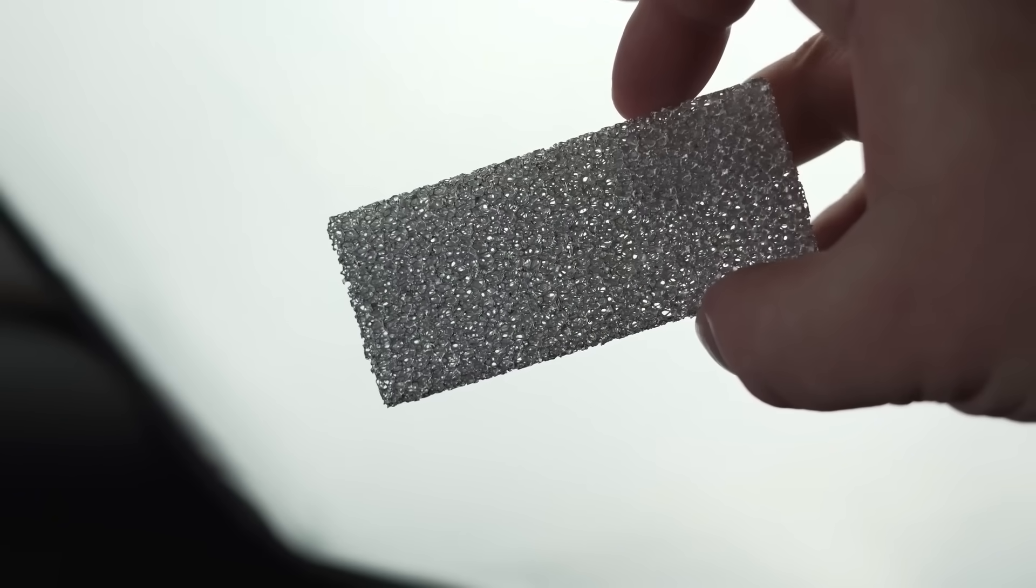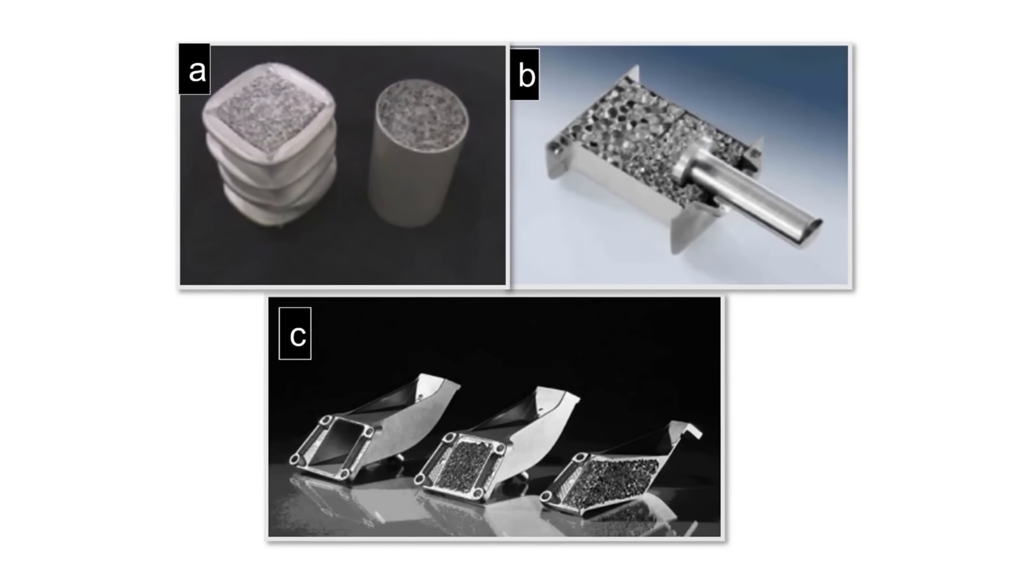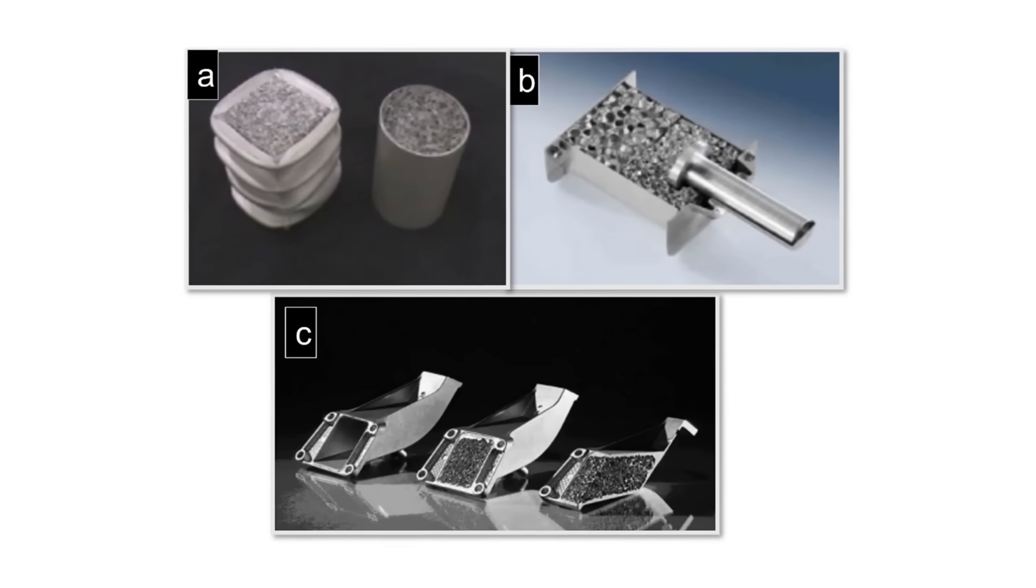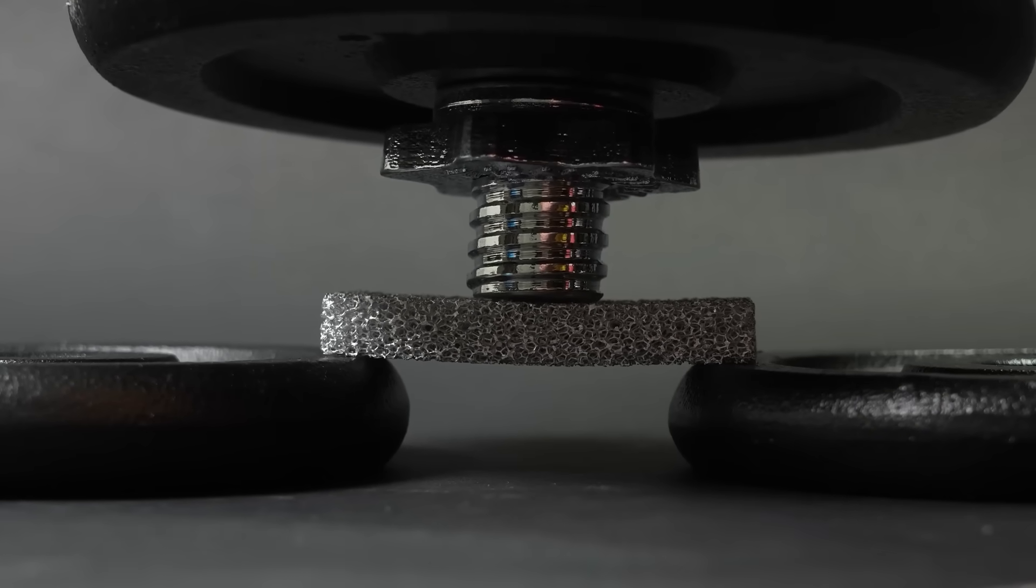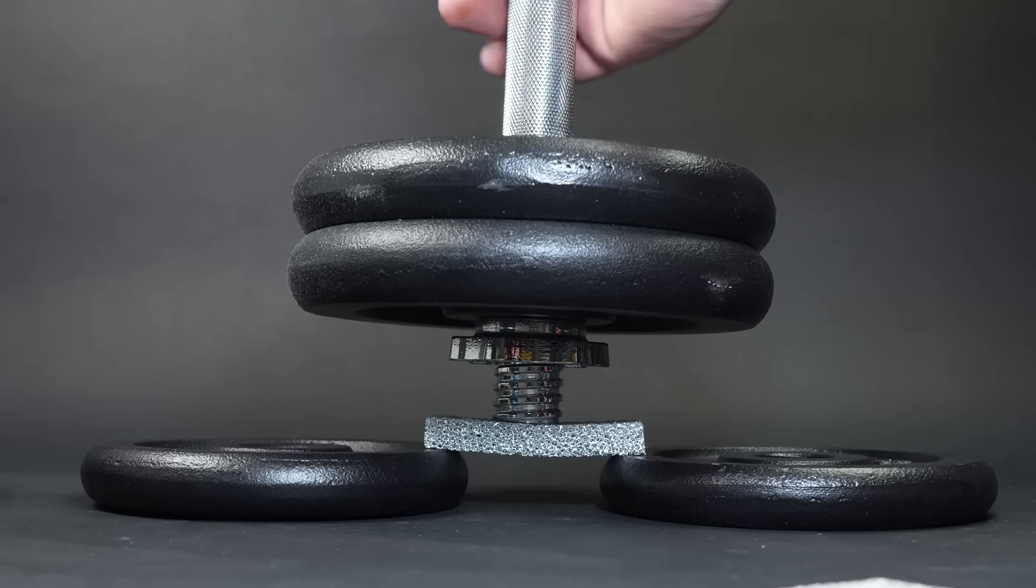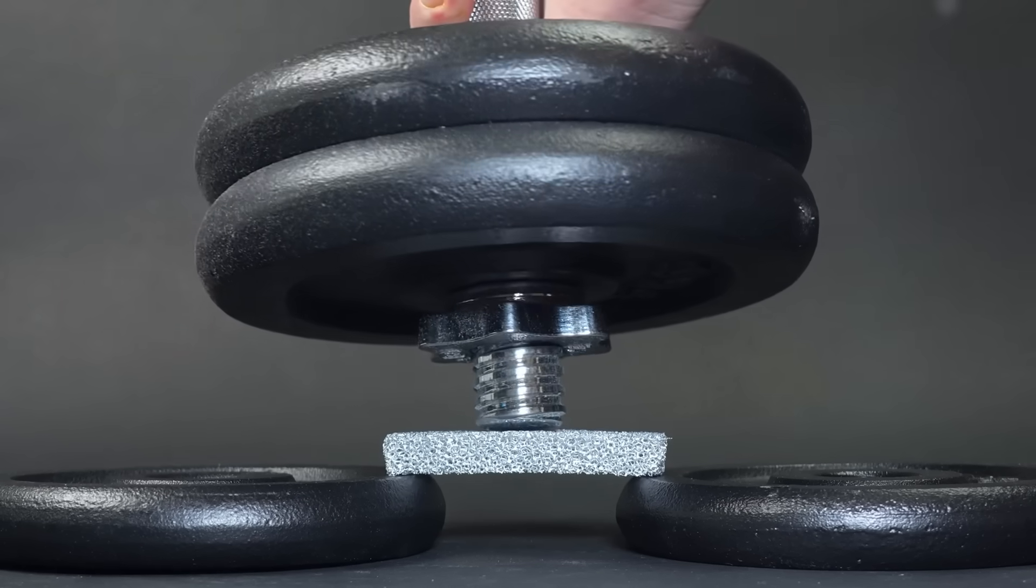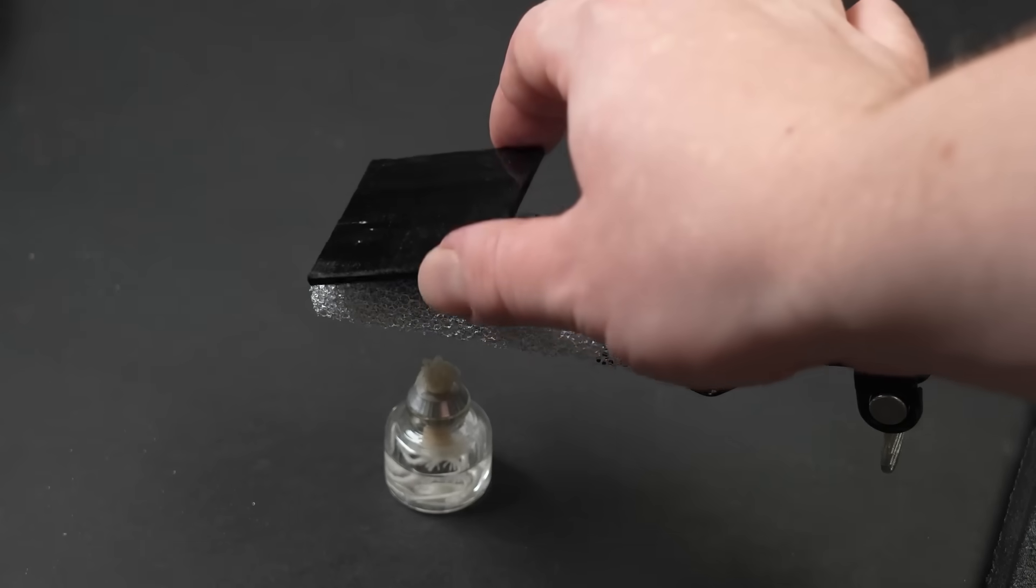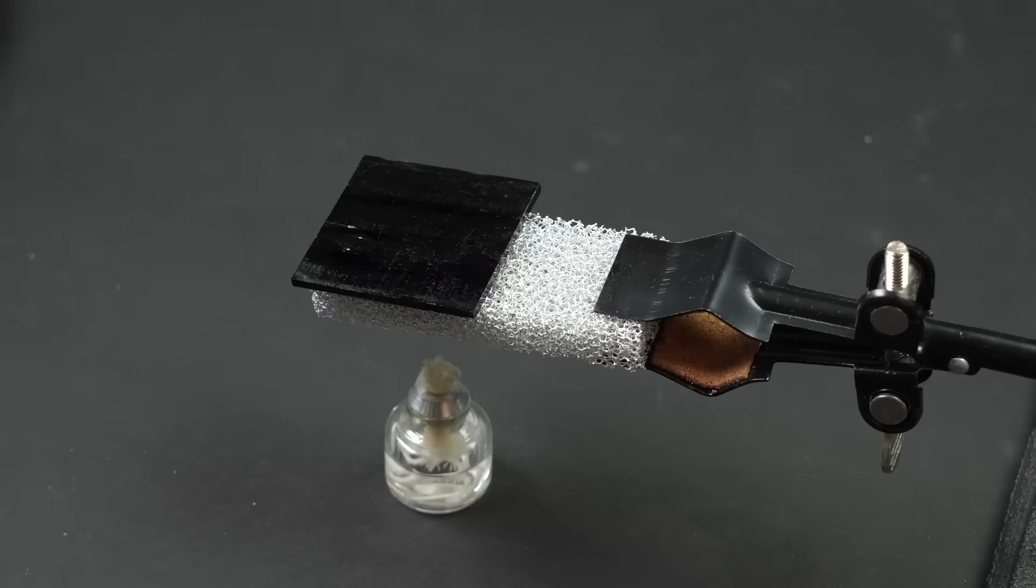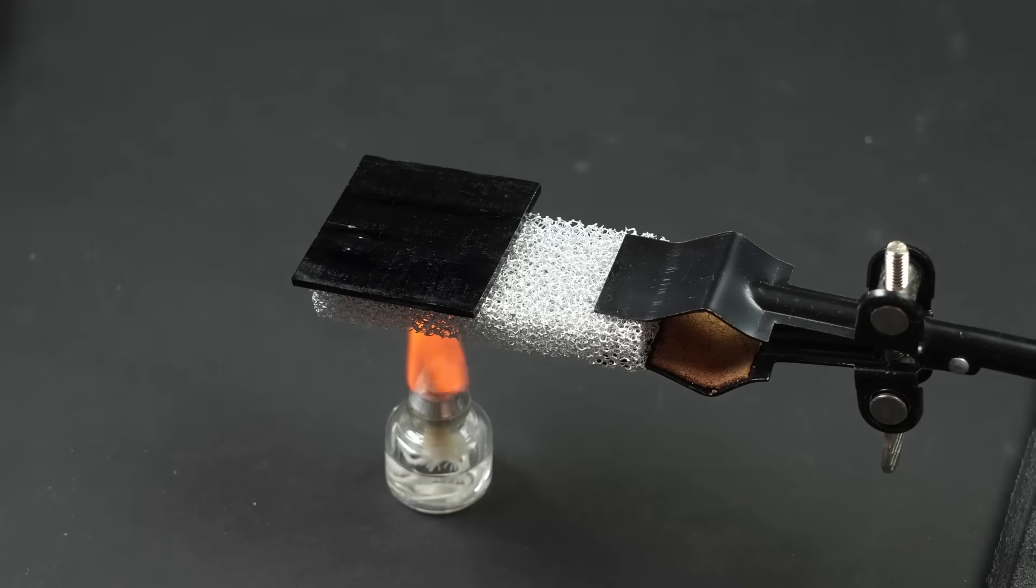Now I'm heating the metal in the furnace again to a temperature of 760 degrees Celsius, after which I add the titanium hydride to foam the metal. I think everything is going much better now. Aluminum really starts to foam up from the hydrogen released by the decomposition of titanium hydride. According to the instructions, the foamed aluminum needs to be constantly stirred, although, in my opinion, it just ends up bursting the hydrogen bubbles inside the metal.